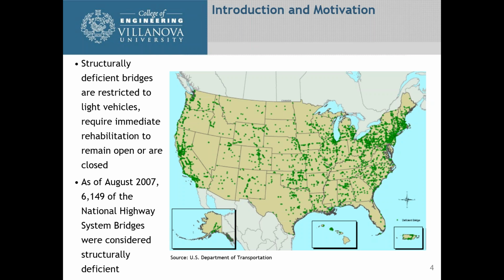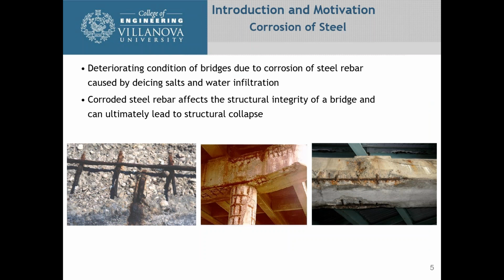So why are we looking at doing this study? As of August of 2007, there were over 6,100 structurally deficient bridges in the United States, and a lot of this has to do with corrosion of the reinforcing in the concrete. In the areas where there's a lot of chlorides used for de-icing salts, you get cracking in the concrete decks, and the water with the chlorides in it infiltrates into the concrete and starts to corrode the reinforcing bars. And you get spalling, deterioration, loss of section.